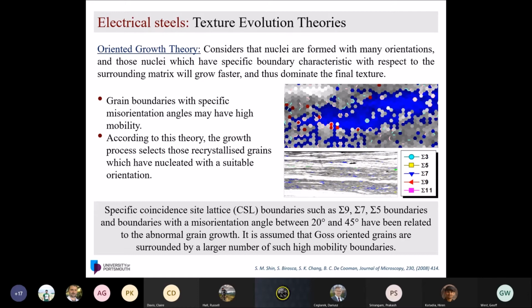And there are other people who think, okay, ignore the CSL boundary, but the boundary between 20 to 45 degrees is related to the abnormal grain, and they assume Goss grains are surrounded by high angle grain boundary between 20 to 45, where they have higher mobility than the others.